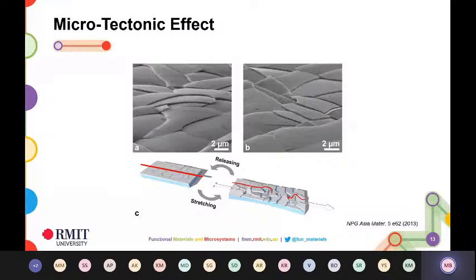So when you look at this, you kind of realize what happens, because when you're applying strain, you have the plates moving apart from each other. But as long as the plates are making contact with each other, you're still having a functional device. Beyond a point, if you apply too much strain, plates lose contact with each other. But then once you release it back, they can slide on top of each other again. So we call this a microtectonic effect, because it looks similar to the plates making up the geological crust. And we thought this is a unique thing which we got out of the transfer process. So not only did we manage to transfer it, we also managed to transfer it in such a shape and form that it's able to withstand some strain now.